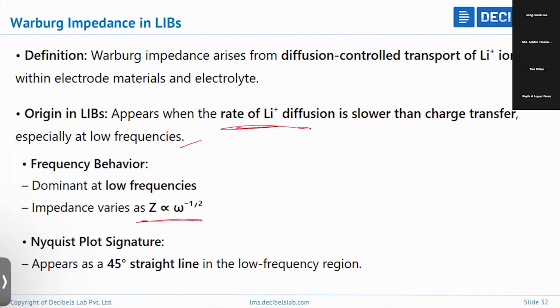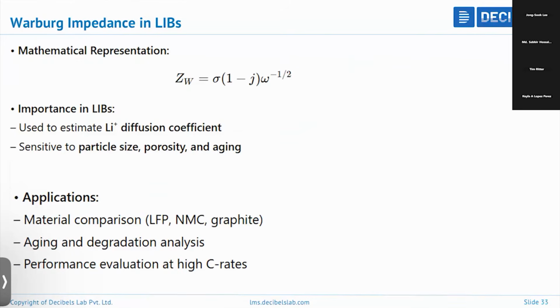The impedance is directly proportional to omega to the power of minus half. So the mathematical representation of the Warburg is equal to sigma into (1 minus j), this j is the imaginary component, into omega to the power of negative, that is minus half. So it depends on the diffusion coefficient. So this information is used to estimate lithium-ion diffusion, and it is sensitive to particle size, porosity, and age.